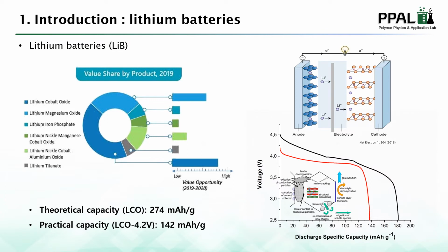So to maximize the electrochemical performance of the lithium batteries, the upper operating voltage should be increased to 4.5 volts, which is generally known as the theoretical working potential, a high voltage working condition. However, this induces some serious problems such as the oxidation and decomposition of electrolyte and active materials, which ultimately damage the physical-chemical stability of the batteries. And therefore, to realize high voltage stable lithium batteries, the aforementioned problems of the solid state and high voltage working condition should be thoroughly resolved.